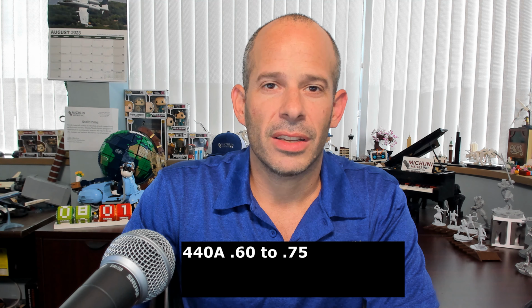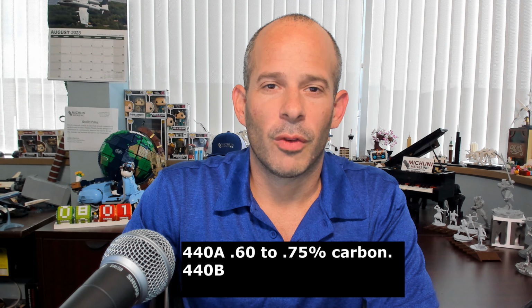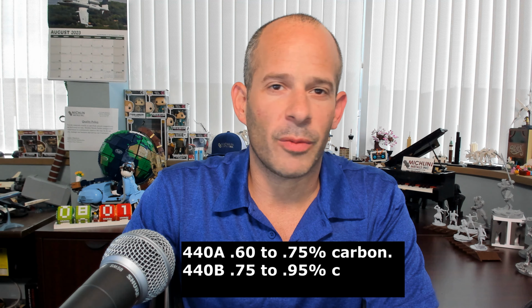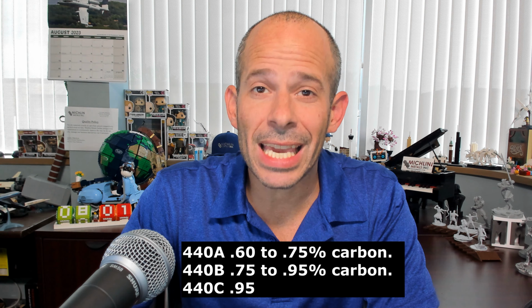Lastly, we have a group of alloys in the highest range of carbon in the Martensitic series, the 440s. Chromium content is 16 to 18% and has 3 variations with differing carbon content. The higher chromium content improves corrosion performance over Type 420 and 410, and the higher carbon increases the strength and hardness capability. 440A has 0.6 to 0.75% carbon. 440B has 0.75 to 0.95% carbon. 440C has 0.95 to 1.25% carbon.